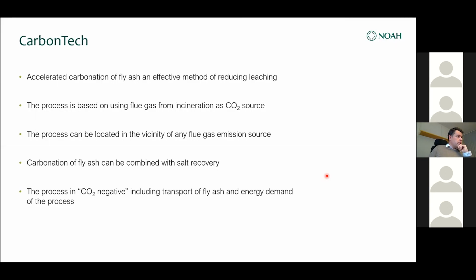That is the salt. Then I move on to what we call carbonate. Accelerated carbonation of fly ash is an extremely effective method of reducing leaching in fly ash. Now we are using sulfuric acid to stabilize fly ash, but you can also use HCl or CO2. The mechanisms are more or less the same. And this process is based on that you can use flue gas from any kind of incineration as a source of CO2. So this process can be located in the vicinity of any flue gas emission point. So it's very flexible in that sense.